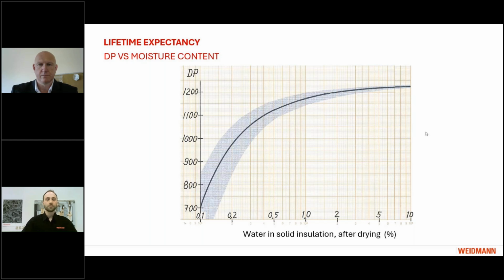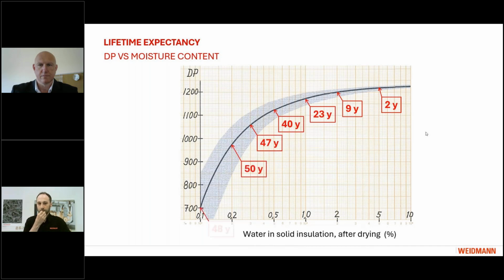Now, if we plot the degree of polymerization as a function of moisture content, and we ask ourselves what is more important, that it is really dry or that the degree of polymerization remains very high, we can see that actually if we are too high in water content, meaning between 2 and 10%, we have a very low lifetime. Then below 1%, we enter a range where the age becomes really nice, some 40 to 50 years. But if we dry it too hard and we get to a really low degree of polymerization, we see that it starts to reduce again.